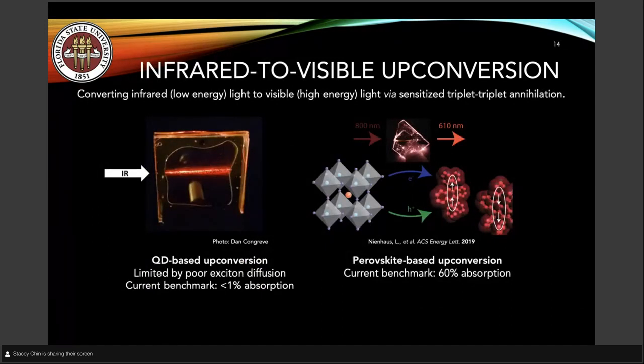Okay, so changing gears a little bit, moving to infrared to visible upconversion. My postdoc was mostly focused on quantum dot based upconversion. And the one issue that we ran into was that a monolayer of quantum dots seemed to be pretty much the best that you could do. And this is caused by poor exciton diffusion. So these long organic ligands that you have around the quantum dots just don't let the exciton wander very far in a thick quantum dot film.